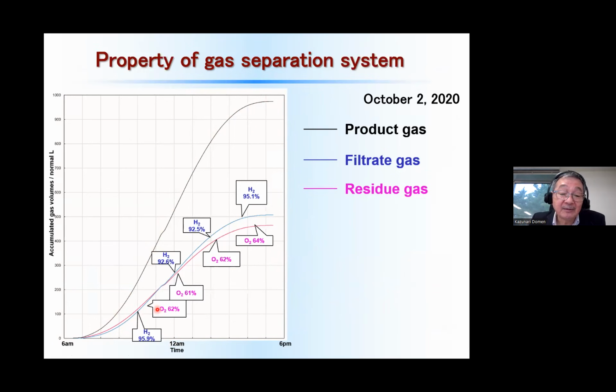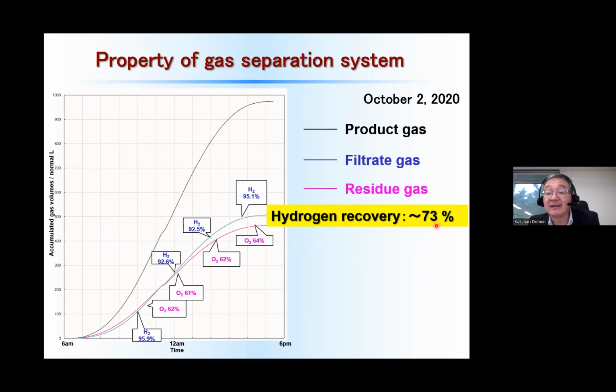Sorry, this is a little bit busy, but this green curve indicates the hydrogen-rich filtrated gas composition. In the morning, we obtained about 96% hydrogen purity. In the daytime, the purity was about 92 to 93%. And in the evening, it becomes about 95%. The difference in purity is due to the ability of the hydrogen separation, because this polyimide membrane's separation property becomes worse when the temperature is higher. From these curves, we obtained that the hydrogen recovery was about 73%.